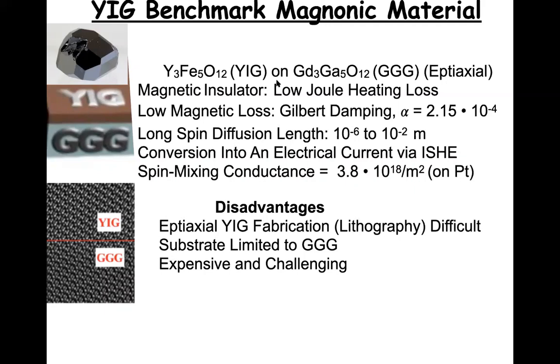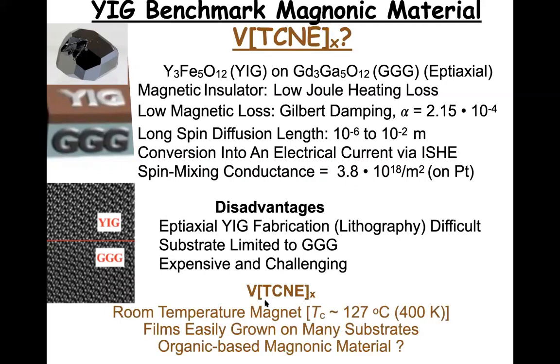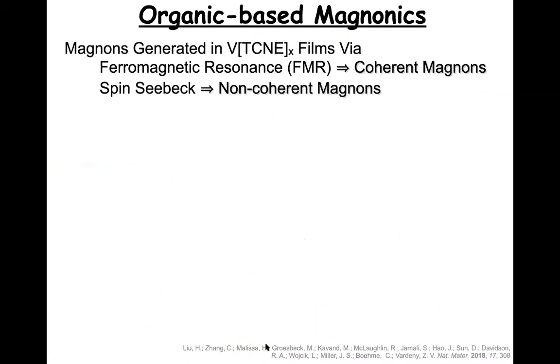So the question we raised is, can we make vanadium TCNE as a magnetic material? I just told you it's a magnet that orders at 127 degrees. And in fact, you can grow it on many substrates. And can we make an organic-based magnetic material? Well, I'm going to simply summarize a full talk on this by saying, yes, magnons can be generated in our vanadium TCNE film, and we can detect coherent magnons using ferromagnetic resonance. We can detect non-coherent magnons using the spin-Seebeck effect.